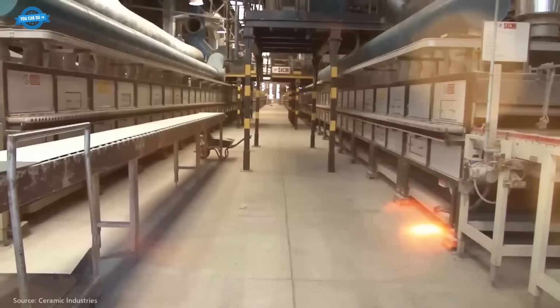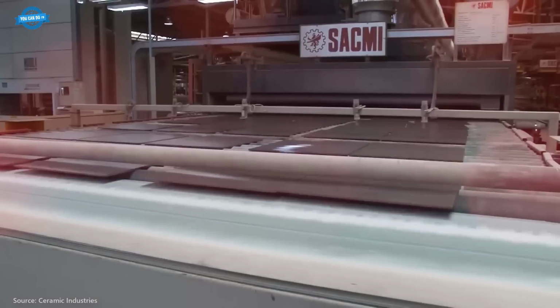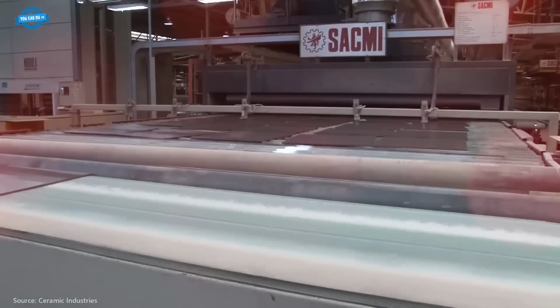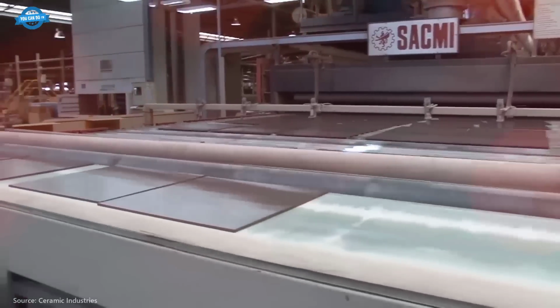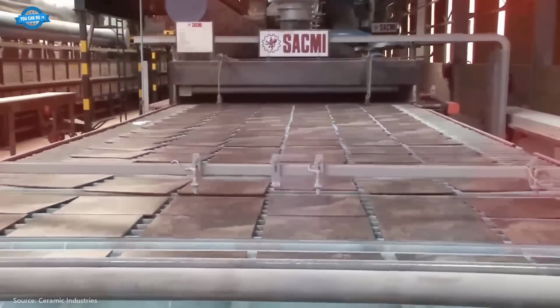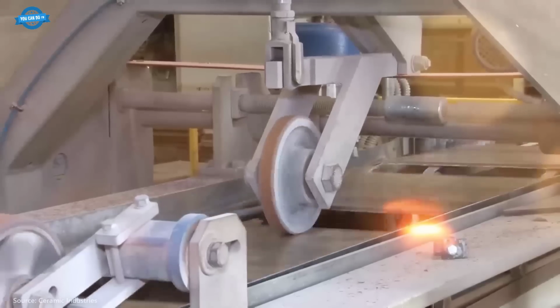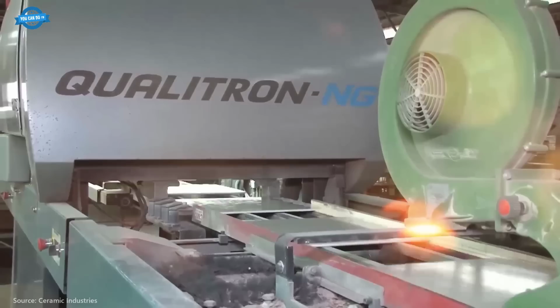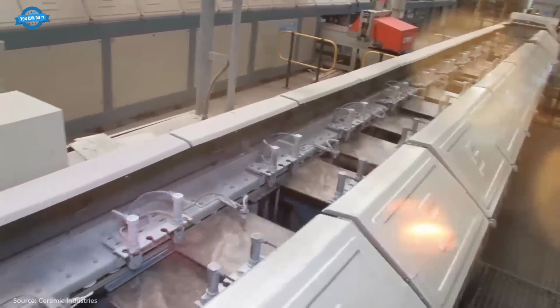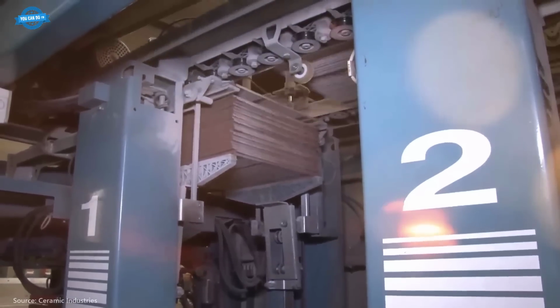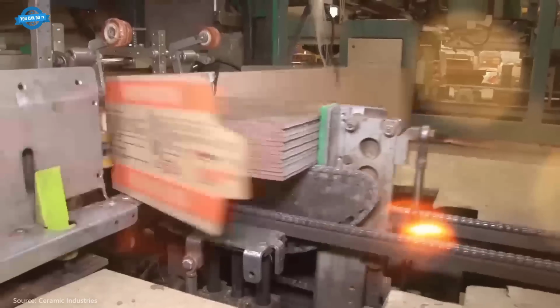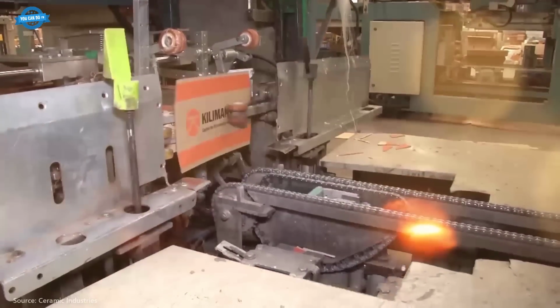Firing and finishing. Tiles are fired in a kiln, where temperatures reach 1185 degrees Celsius. This step hardens the clay and ensures durability. Gradual cooling prevents warping or cracking due to thermal shock. After firing, each tile is inspected for quality, graded, and sorted by robotic machinery. The factories operate 24/7, producing up to 500,000 tiles daily for both domestic and international markets.